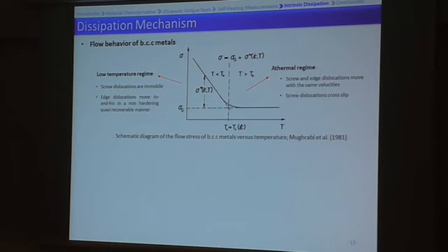It's well known that for BCC metals, there are two major deformation modes based on the transition temperature as defined schematically by Mughrabi and his co-workers in this diagram. You can see that below the transition temperature, we are in low temperature regime in which screw dislocations are immobile and edge dislocations move to and fro in a non-hardening, quasi-recoverable manner. In contrast, for the temperatures more than T0, which is the transition temperature, we are in the athermal regime in which screw and edge dislocations move with the same velocities, and moreover screw dislocations can cross slip.